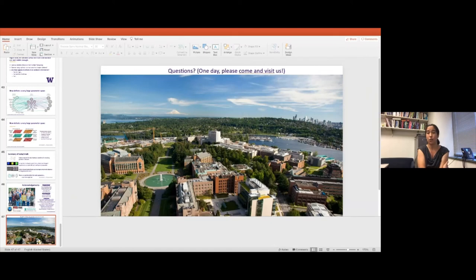There's another area of my research that I didn't talk about that's very exciting. We are now using these same types of nanophotonic platforms to do very efficient frequency conversion. When you do frequency conversion, you are mixing in a coherent field to create a single photon at a new frequency. If you have two photons at different frequencies and you convert them to the same frequency, it turns out that erases which defect they were emitted from, the which-path information, and you can entangle those two different defects. So at the same time, while we're trying to get those materials better, we're also coming up with engineering solutions where the materials don't have to be exactly identical.